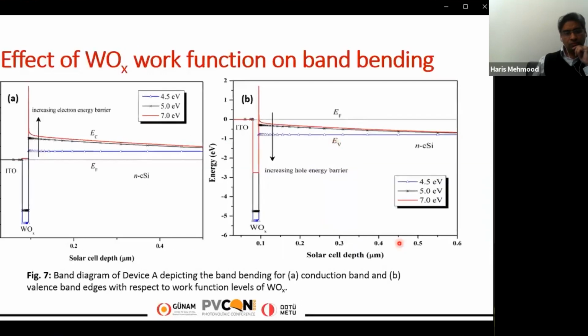Now the effect of the tungsten oxide work function on the band bending. We can see that upon increasing the work function of tungsten oxide, the energy barrier against the minority electron is increasing at the top anode interface. If we decrease the work function of tungsten oxide, as shown in blue color, as we can see for the conduction band, this is shown on the left side is the conduction band figure, and on the right side is the valence band figure.